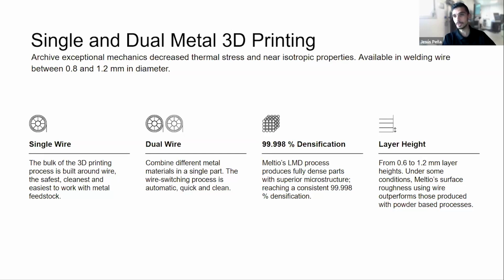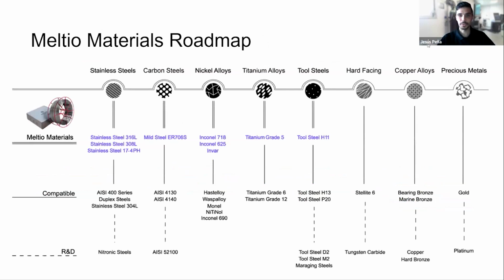Also, about layer height, in our LB-DED deposition process, we are focusing on layer heights from 0.6 to 1.2 that we have found are really stable layer heights that we are able to hold with our technology, and also with the wire range that we are using with the welding wire, I mean. So those are some of the samples of materials that we have already developed.